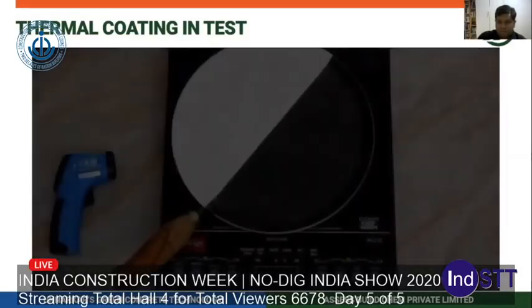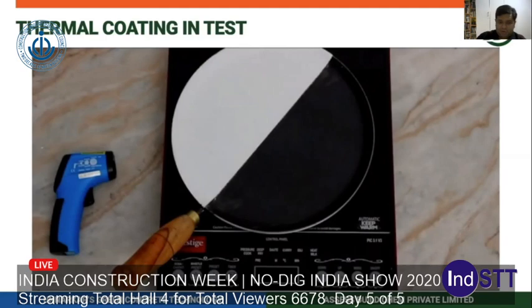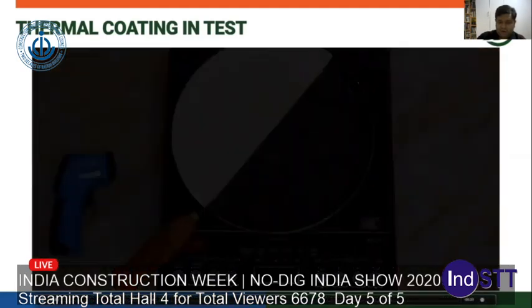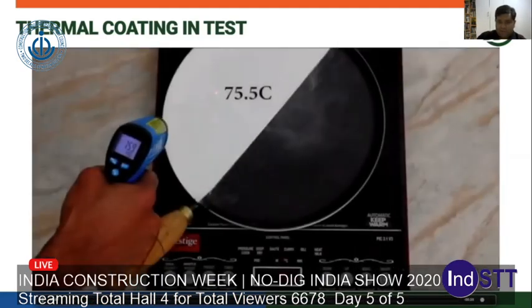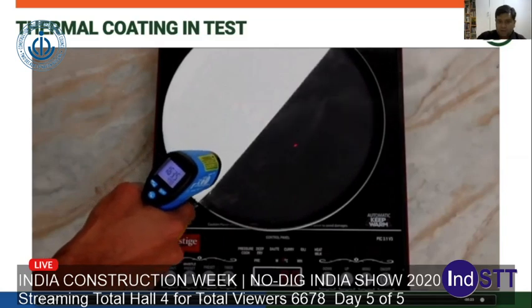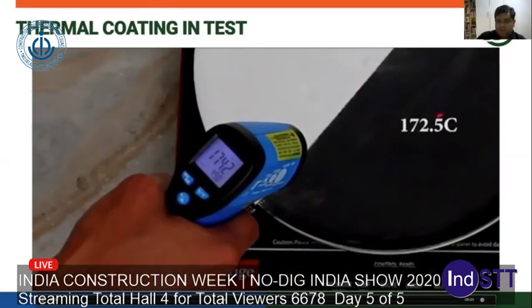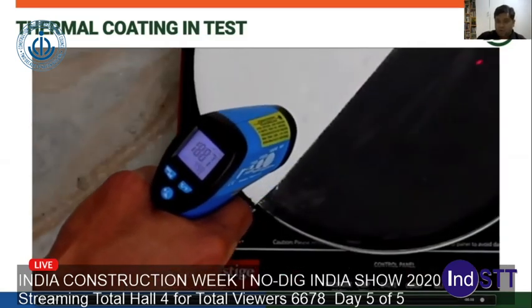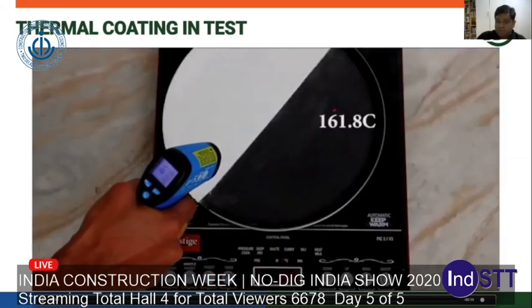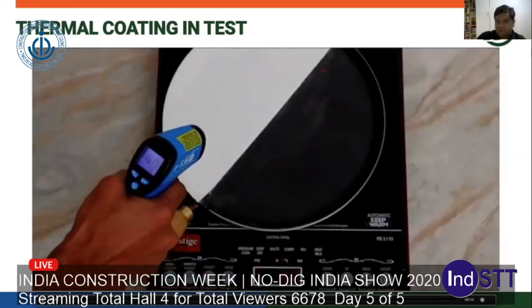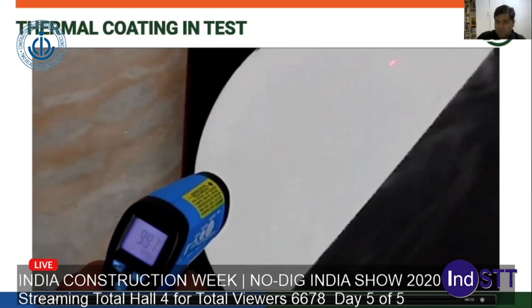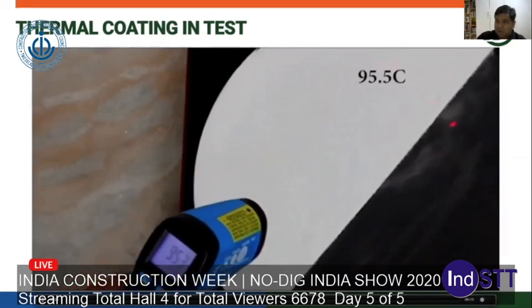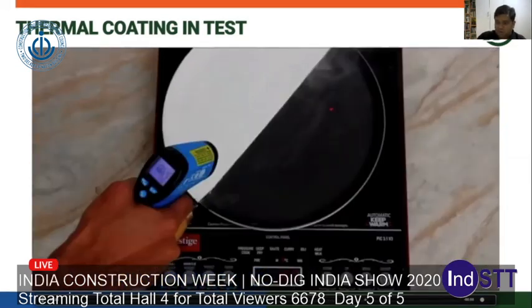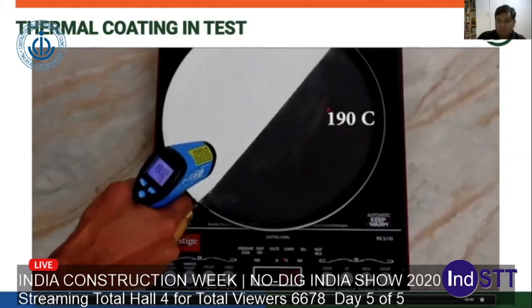Just to see it in terms of a test, what we did was a simple test we call a griddle test. We just take a griddle and heat it up. You can see that on the coated side it is about 95 degrees, and on the uncoated side it's going up almost to 175 degrees. That's quite a lot of heat to be reduced. This is of course not a building condition. A building will never get heated to those kinds of temperatures, but it gives you an idea of the efficiency of these kinds of coatings.